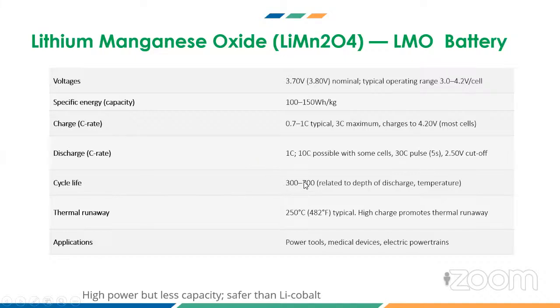Another drawback of this one is cycle life is less. It's one of the major drawbacks. That means we cannot use the battery more than 2 years. And when compared to the cobalt battery, this can withstand up to 250 degrees centigrade. So from a safety point of view, it is better. The major drawback of this lithium manganese oxide battery is less capacity.